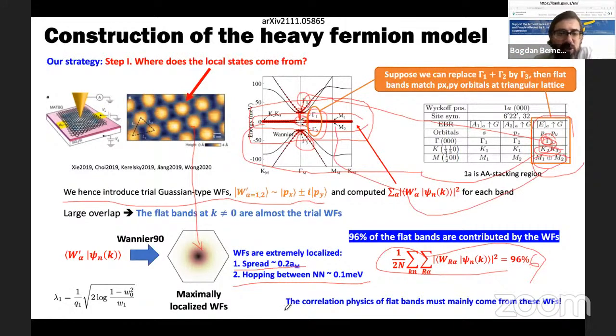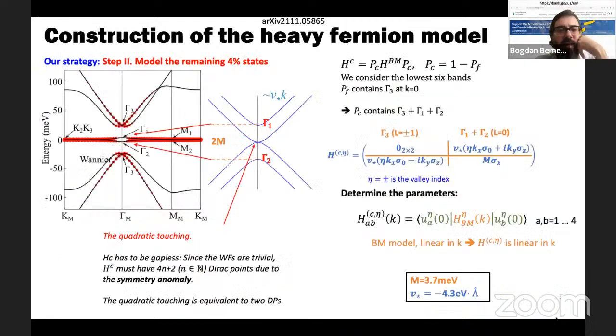And hence we conjecture, and now we'll prove, that the correlation physics must come from these flat orbitals, which are localized and will have high Coulomb interaction, as we'll show. And these are called the f-electrons or the heavy fermions. Now, we want to model the remaining 4% of the states, because if we just had these localized electrons, we couldn't get superconductivity or topology. The remaining 4% of the states can be modeled in the following way.